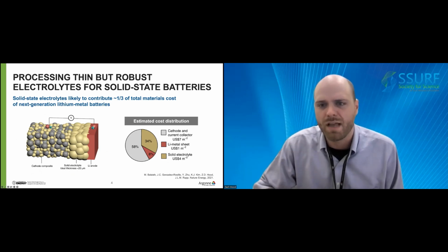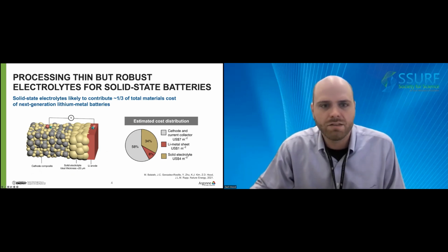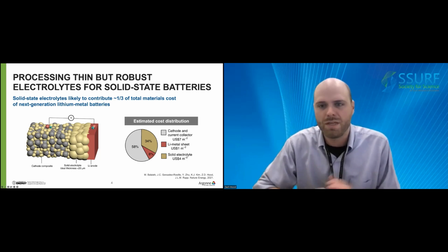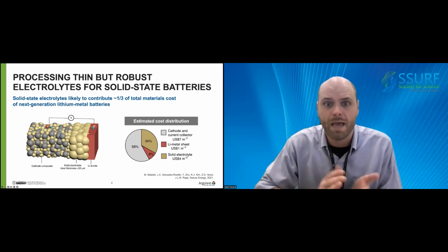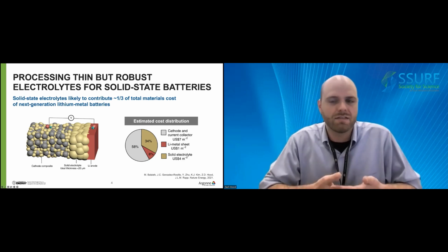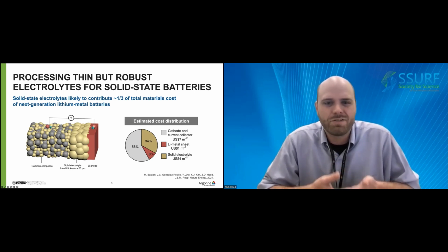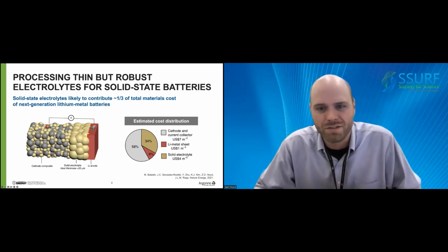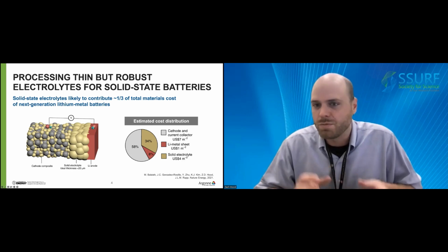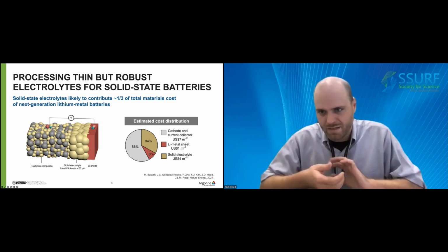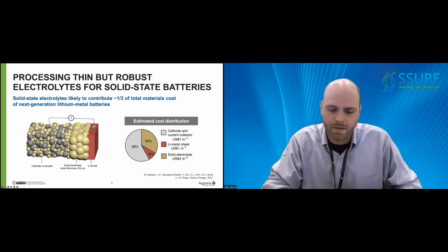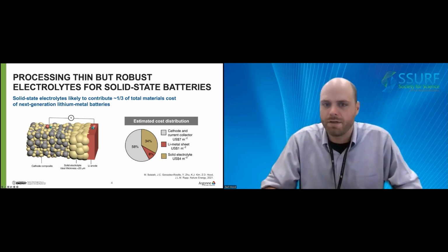this solid-state battery stack. So if we consider the length scales and form factors of different cell components, we can estimate the cost distribution for these batteries. When considering the solid-state electrolyte, this component is likely to contribute to around 1/3 of the total materials cost. However, these cost estimates are based off of using 20 micron thick solid-state electrolytes, which are around 1/4 the diameter of your hair. But in terms of these cost estimates, it really motivates my work because they are quite significant for these next generation batteries, and we must consider this moving forward.